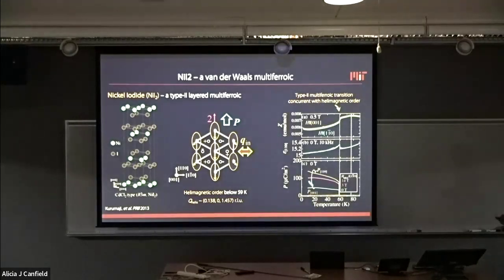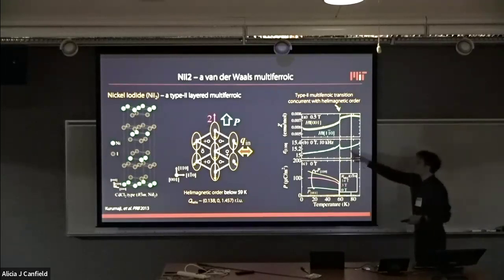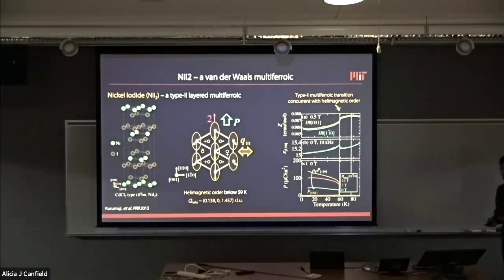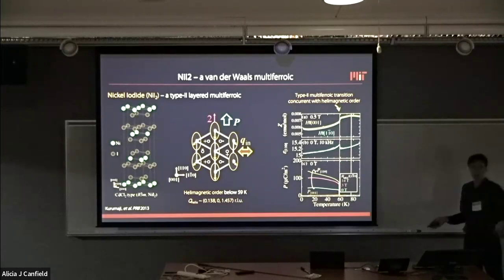This has been studied by the Kimura group originally in the bulk, also more than 10 years ago, and there is a multiferroic transition, or a magnetic transition. You can see the susceptibility at about 59 Kelvin. There's also a higher temperature transition, but I'm not going to discuss that today. And then you see a dielectric anomaly at the same transition. So this already signals that the charge degrees of freedom are responding to the formation of spin helical magnetic order. And this can also be further tuned with the magnetic field. So this is a direct signature of magnetoelectric coupling.